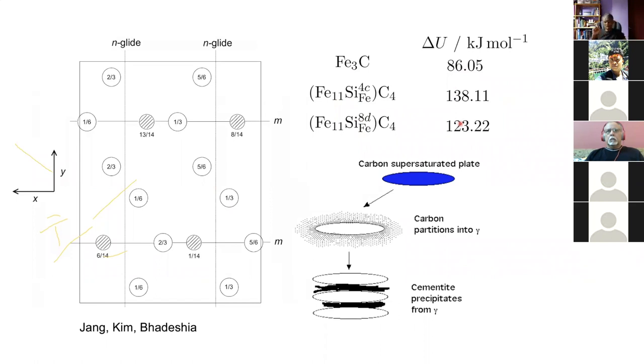First-principles calculations are at their best when there is nothing else you can do. These are calculations at zero kelvin and zero pressure, but there is no choice — this is the only way to get the necessary thermodynamic information. Nowadays thermodynamic databases include results from first-principles calculations, which look at electron theory to work out energetics.